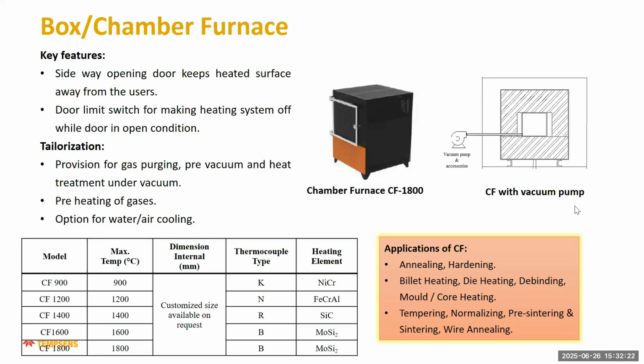For CF 1600, we have a maximum temperature of 1600. The thermocouple type can be B, and the heating element can be molybdenum disilicide. Then we have a model CF 1800, which can go up to 1800 degrees centigrade. The thermocouple type can be B, and the heating element will be molybdenum disilicide. Applications of the CF furnace can be annealing, hardening of big material, billet heating, die heating, debinding, mold and core heating, tempering, normalizing, pre-sintering, sintering, and wire annealing.